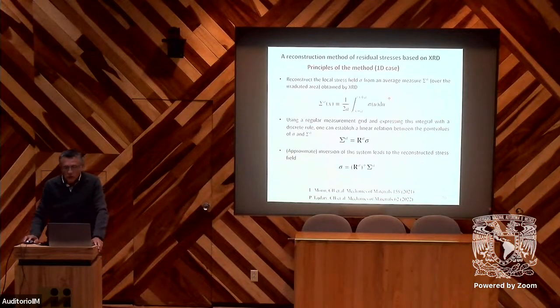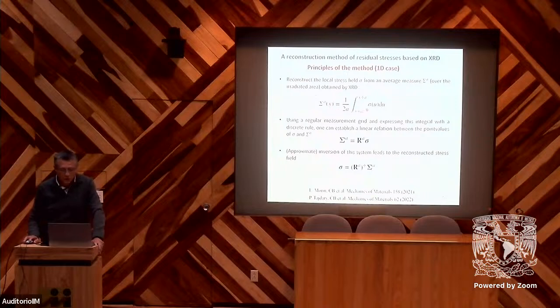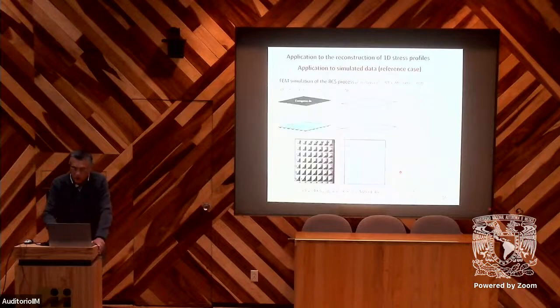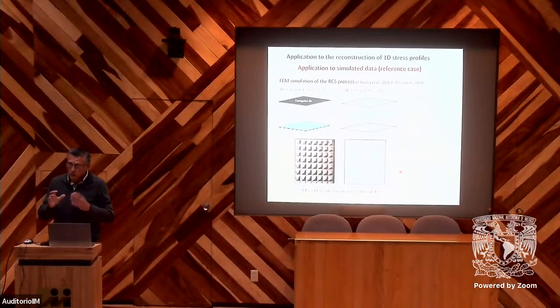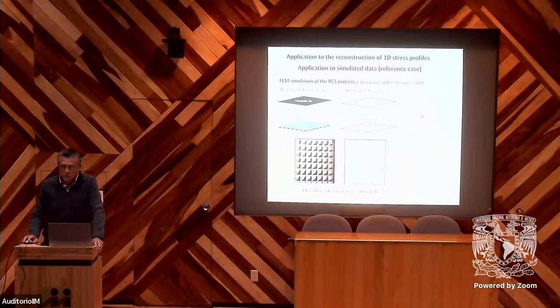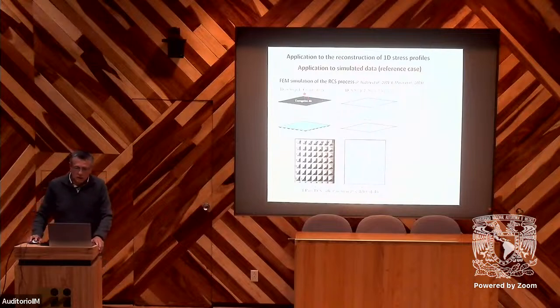So for this, we developed a new method to rebuild the residual stress map or line from average measurements. That means for this method we need to determine the local stress from the average measurement. For this, we consider that we have regular measurements, and then we can use an inversion of the system to get the local stress from the average value. But for better results, we need to measure using two different spot sizes. We applied this to a severe plastic deformation process. This is the RCS process.